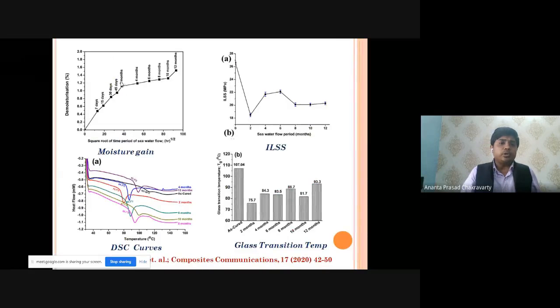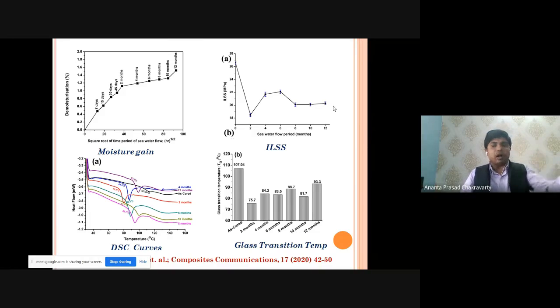See that up to 2 months the moisture gain increases. From 2 months to 10 months the moisture gain is very reduced. That means I can use these pipes with a very sustainable experience. Then from 10 to 12 months the moisture gain increases. But at that level, though the moisture gain is increased, see the ILSS is constant from 8 months to 12 months. That means it is stagnant. The graph is not extrapolated here. That means its strength is not decreased, and it has an increasing trend. That means I can use it beyond 1 year also.